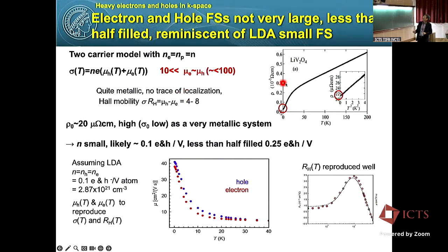And first of all, we do see quite metallic behavior. To have that kind of metallic behavior, we need a mobility of at least 10. And the Hall mobility is like a difference between the two mobilities, and this is 4 to 8. So mobility must be much larger than 10, right? But our residual resistivity is roughly 20 microohm centimeter always. And this is kind of high for a very metallic system.